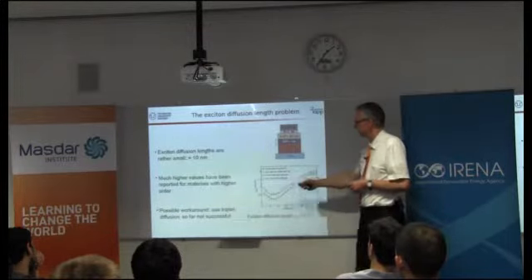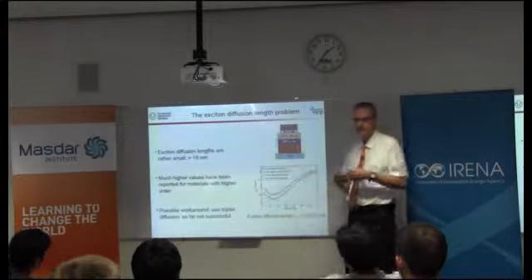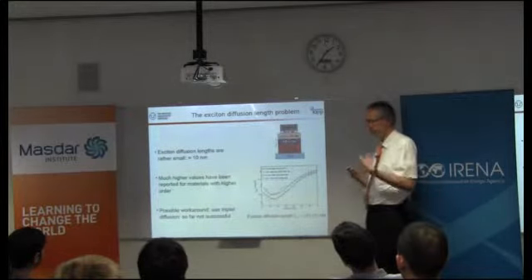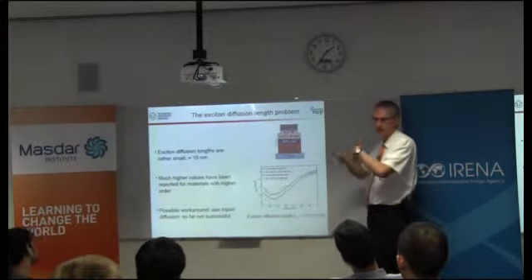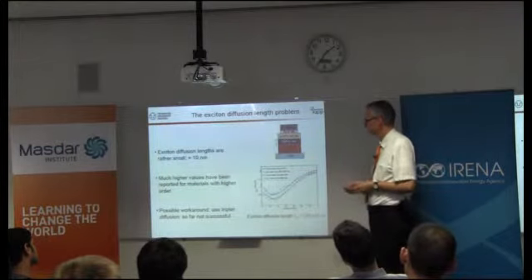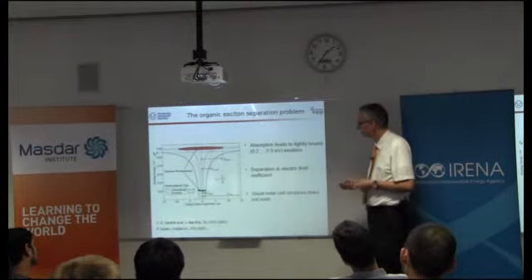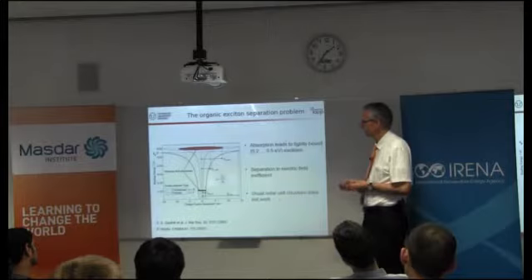And the best fit is 10 nanometers. So these excitations can move only a very, very small distance. In silicon, they can move hundreds of microns. And the second problem is, as I said, the tightly bound exciton.